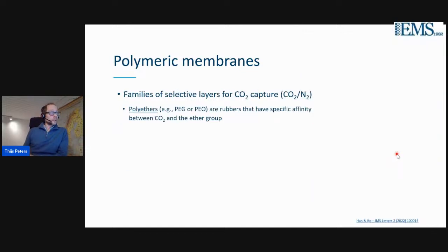So for polymeric membranes relevant for CO2 capture, where CO2 is typically removed from the flue gas, the polymer needs to be selective for CO2 over nitrogen. Here, the membrane typically is made of polyethers, so polyethylene glycol or polyethylene oxide rubbers that have a specific affinity between CO2 and the ether group constituting the ethers. This means that it's highly soluble for CO2 over nitrogen, and in case it also has a high diffusivity, it becomes permeable for CO2 in a selective manner over nitrogen.